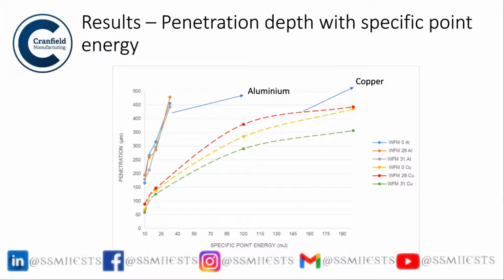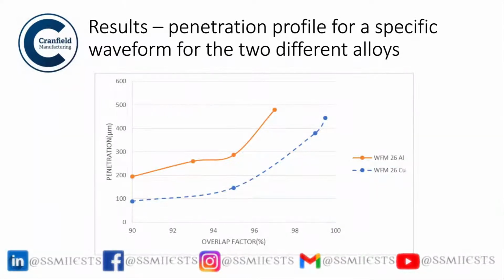So in the bead on plate result, as you can see, for the same application of energy, you get much higher penetration in aluminium as compared to copper, which is not surprising because copper is highly conductive and the temperature rise is rather slow in copper as compared to aluminium. And here this graph shows, for the same type of waveform, how the two alloys respond to the heat.